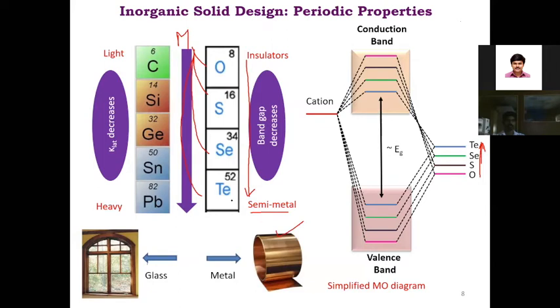And as this is still a semiconductor, because it has a small band gap, it gives a reasonable Seebeck coefficient. So we have two properties satisfied down the periodic table. Now if we construct the lattice with heavy metal like lead or tin or tellurium or selenium or even germanium, the lattice vibration becomes slow, because with heavier elements the lattice will vibrate very slowly and give rise to low phonon velocity. That means low thermal conductivity. We will get glass-like thermal conductivity if we construct the lattice with heavy metal.